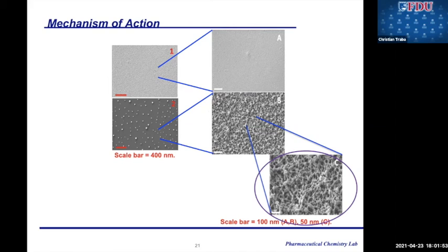So let's go back to image 1. Once again, image 1 demonstrates uniform polymer brush coverage with no cross-linking. However, as silver nanoparticles were immobilized onto the grafted surfaces, and as seen in image 2, multiple attachment sites between the polymer brushes and the silver nanoparticles are apparent and were confirmed in ATR-FTIR peak shifts.